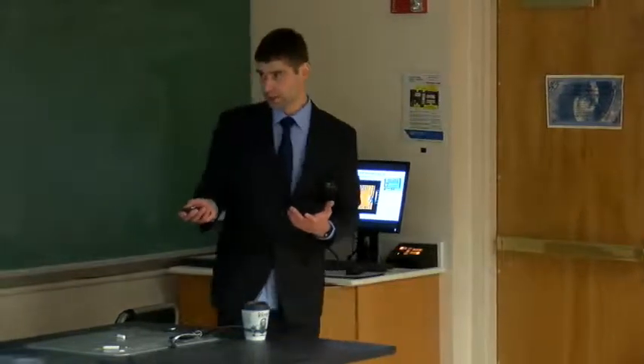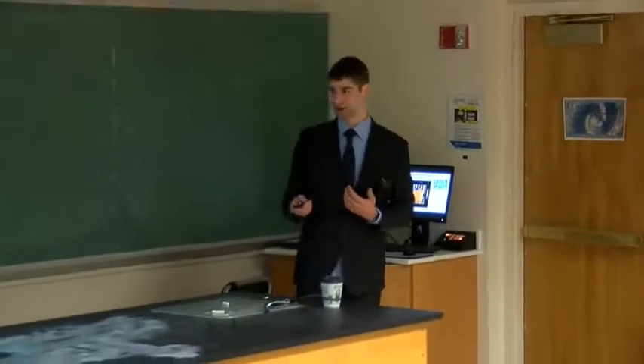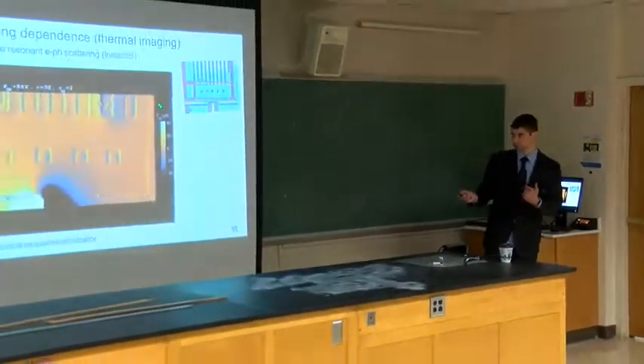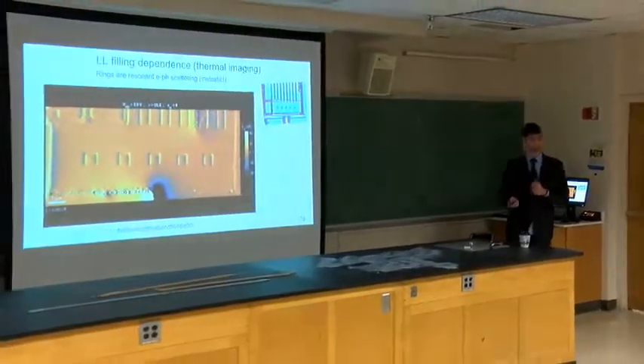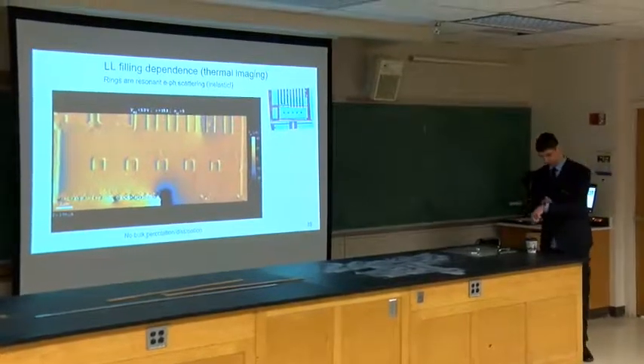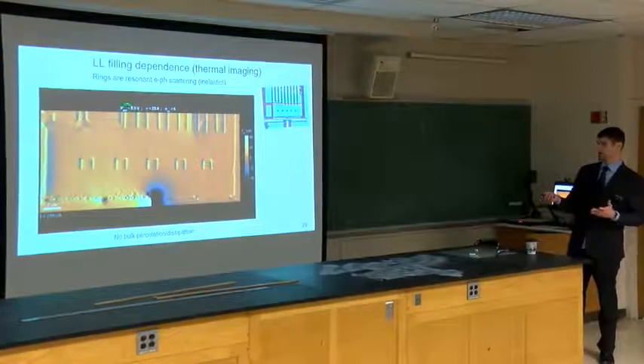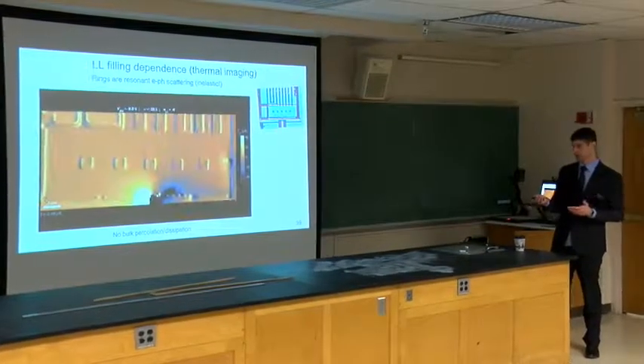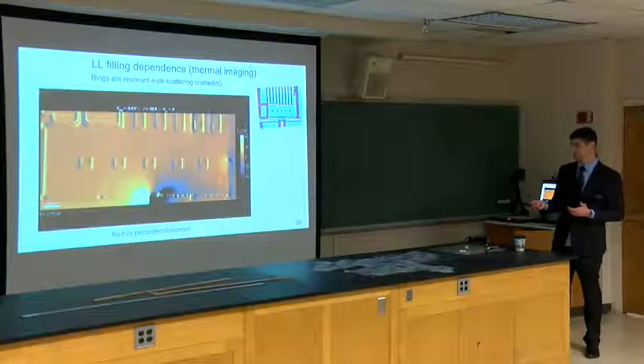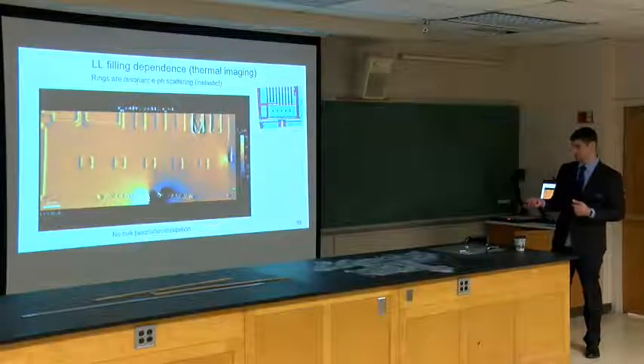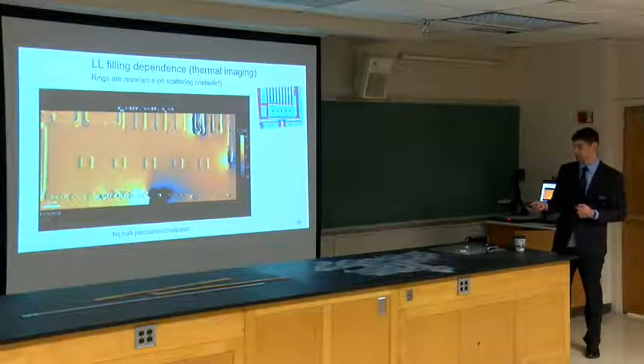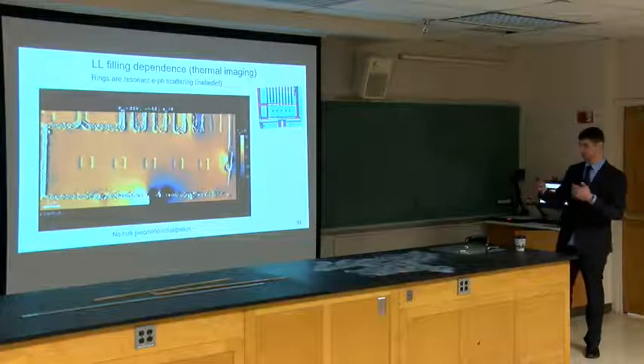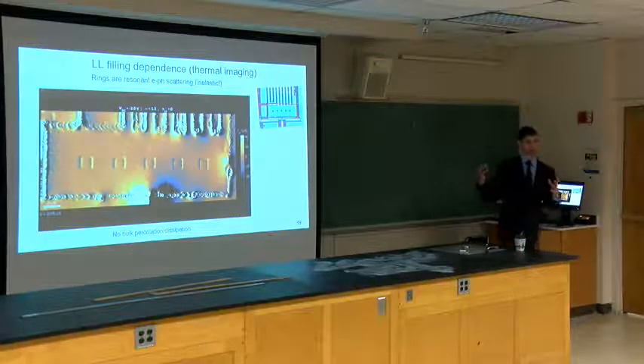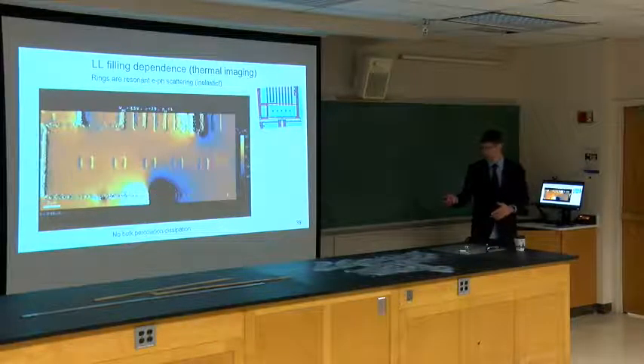Okay, so this strictly gives us temperature data, and it tells us, well, maybe our idea about what's actually going on in the quantum Hall effect needs a little bit of adjustment. And it also has a very strong dependence on filling factor, if you notice this further. So firstly, at higher filling factors, when the density or the number of levels is greater, we see a behavior where it decays. So we see upstream decay, and then as we get closer to charge neutrality, there's a non-local effect happening here, right? There's no decay of this dissipation.